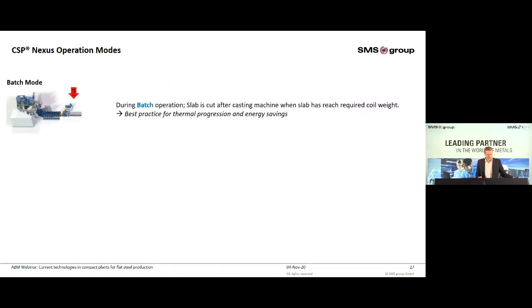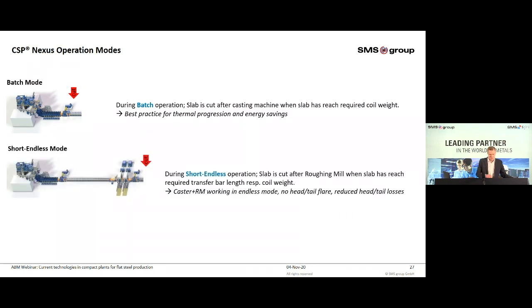This slide describes the 3 different operation modes of the Nexus plant. In batch mode, the slab is cut directly after the casting machine. This is best practice for thermal progression and energy savings. In short endless mode, the cut is made behind the roughing mill. So caster and roughing mill are working in endless. The benefit is that there's no head-tail flare and therefore no head-tail losses on each slab. This will increase the yield of the plant.